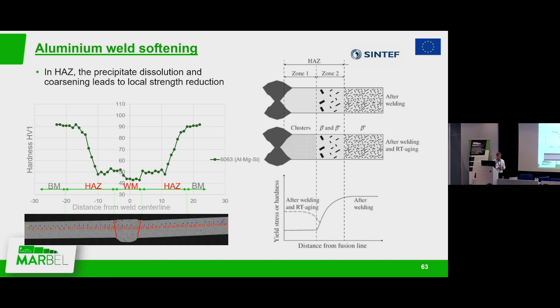So what is the reason for this? In this picture here, we have a laser here. Yeah, there. Sorry. So after welding, the heat from the weld is actually destroying, or in this case dissolving, the small particles, what we call precipitates, that provide the strength of the aluminium. Further away, they are growing and becoming large, and they also don't provide any strength benefits. Further away is the non-affected zone, and this area is as normal, which is good.